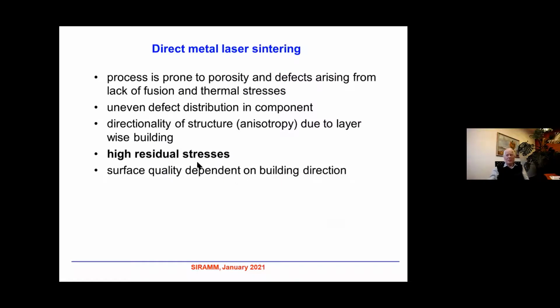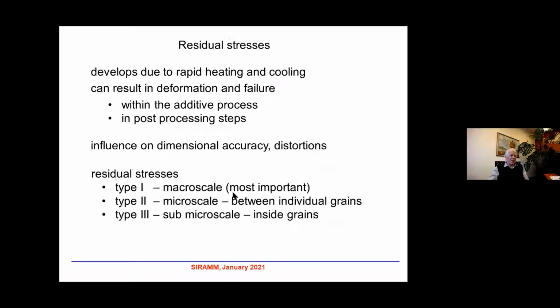Residual stresses. It is also a very important topic. We know that these stresses develop due to rapid heating and cooling. And these stresses can result in deformation of the component, even in failure of the component. So the process has to be designed in such a way as to minimize these residual stresses. They appear within the additive process, but also in post-processing steps. They influence dimensional accuracy, distortions, and so on.